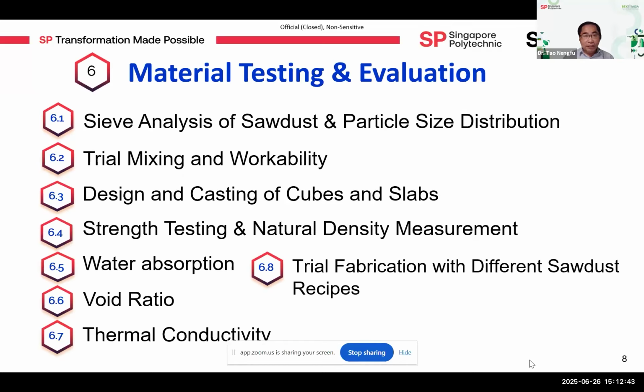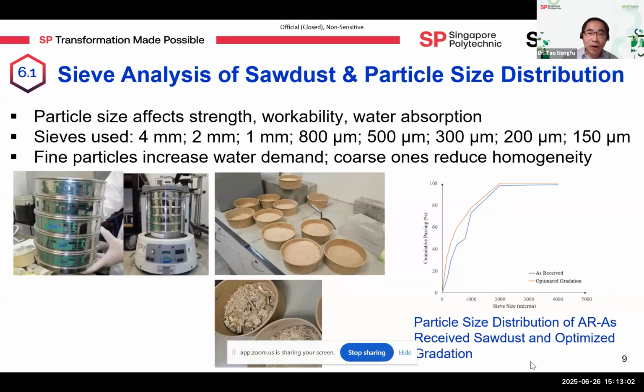We sourced and pre-processed materials, performed mix design trials, and conducted mechanical and thermal performance tests to develop the best formulation. Our testing included sieve analysis, mixing trials, casting specimens, and evaluating properties like strength, density, water absorption, void ratio, and thermal conductivity. As particle size affects strength, workability, and water absorption, we analyzed sawdust using different sieves. The sieve sizes used range from 4 mm to 150 µm. Fine particles increase water demand. Coarse particles, of course, reduce the consistency. Here, the graph shows the particle distribution of AR, which stands for as received sawdust, and OG, which stands for optimized gradation. From the graph, we can see that OG has more fines and a smoother distribution curve than AR.